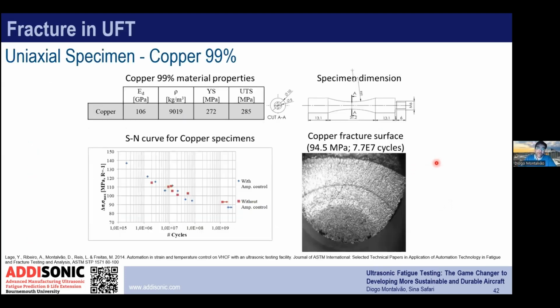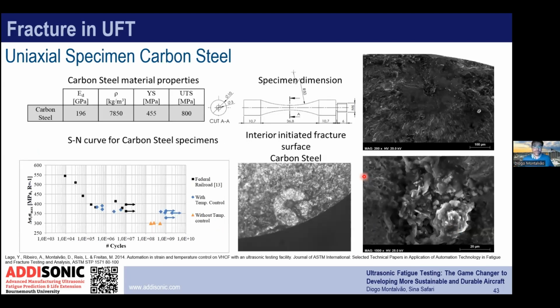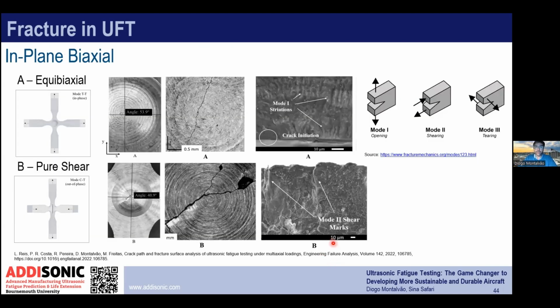You already covered most of the stuff in terms of fracture, so I'm not going to go into details. These are results from the past, from tests we did in copper, and we can see the typical beach marks in fatigue in a uniaxial specimen, and the crack developed from a surface defect. However, in steel, and this comes back to what Sina was just saying about the microstructure, at the very high cycle fatigue regime the crack nucleates many times from inclusions or defects inside instead of surface scratches, in what we call a fisheye pattern. This is very typical in a steel specimen. But you can still see that the data is comparable on the carbon steel specimen.